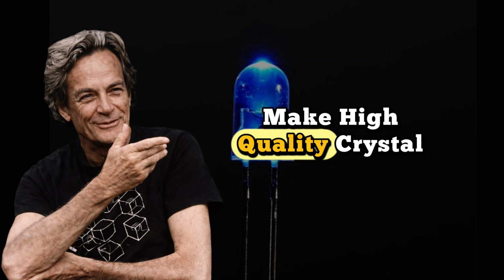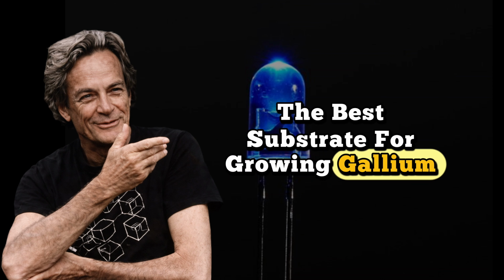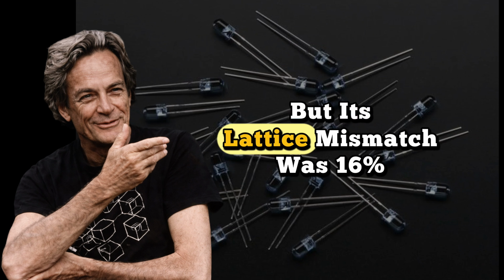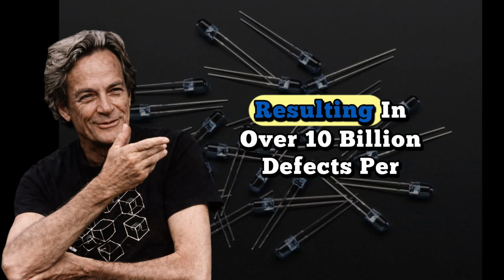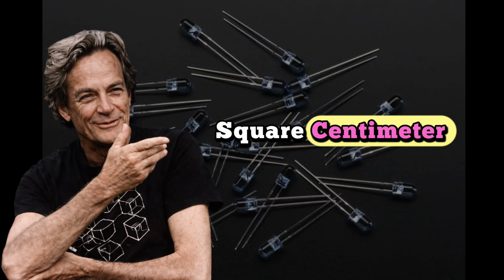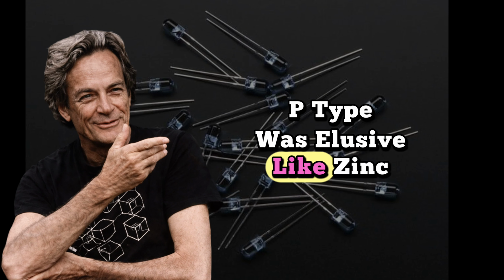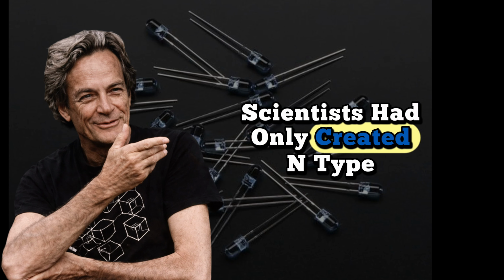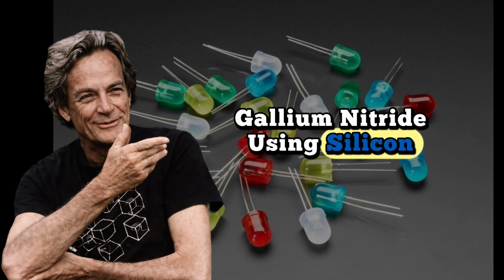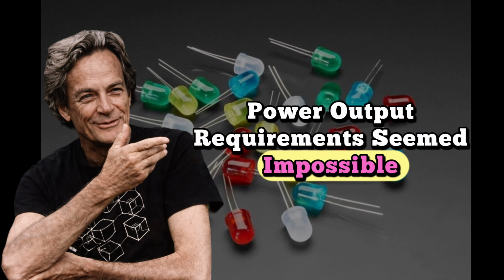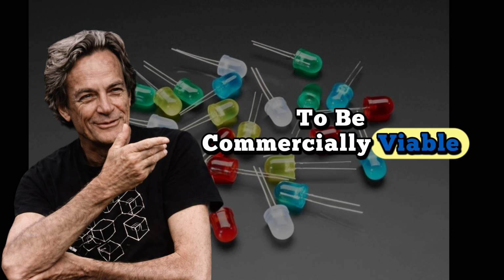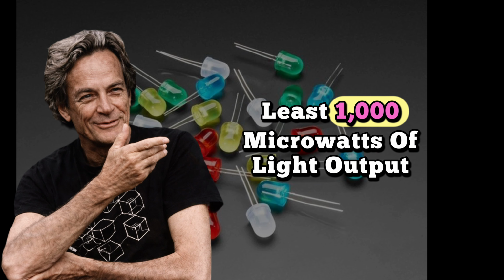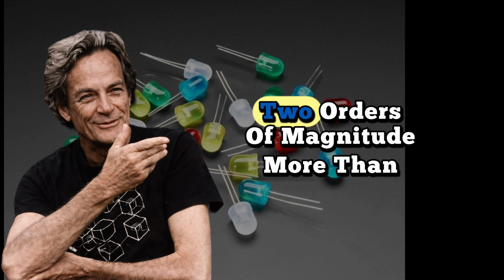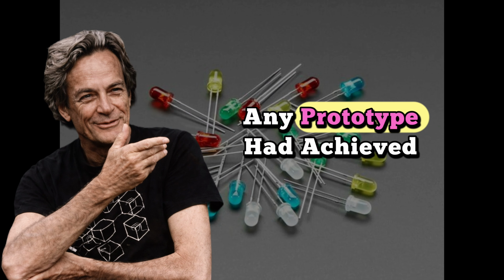Much harder to make high-quality crystal. The best substrate for growing gallium nitride was sapphire, but its lattice mismatch was 16%, resulting in over 10 billion defects per square centimeter. P-type was elusive. Like zinc selenide, scientists had only created N-type gallium nitride using silicon. Power output requirements seemed impossible. To be commercially viable, a blue LED would need at least 1,000 microwatts of light output power, 2 orders of magnitude more than any prototype had achieved.